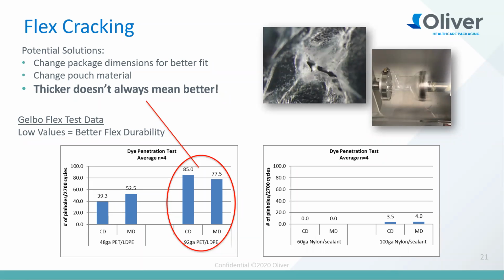On the right, we have nylon. This is 60 gauge nylon. And in that same test, in our simulated environment, it came up with 0 pinholes. The 60 gauge nylon and also 100 gauge nylon have a few, but not as many as polyester. So really the circled area is our prime candidate for this. If you have a concern about flex cracking, the 60 gauge nylon is really the best performing material that we have in our catalog. But also nylon in general is better than polyester, but the message here is, again, thicker doesn't always mean better in this case.